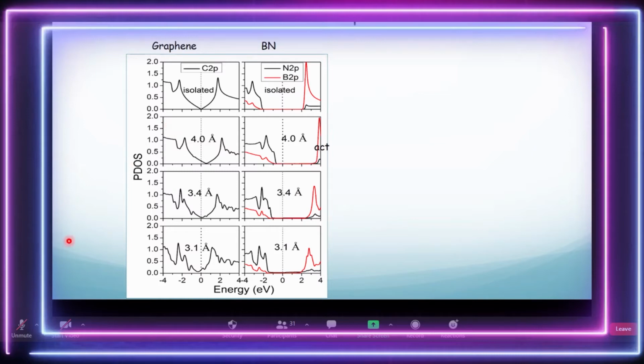So if you look at this case, both for graphene monolayer or boron nitride monolayer, it comes out semiconducting, and you have a finite density of states at 3.1. As you move further, at 4 this finite density of states becomes a really Dirac cone like graphene. And the gap also becomes pretty large here. So indeed, the distance between the contact and our 2D material does play a role in inducing a density of states, in a strong case or weaker case.